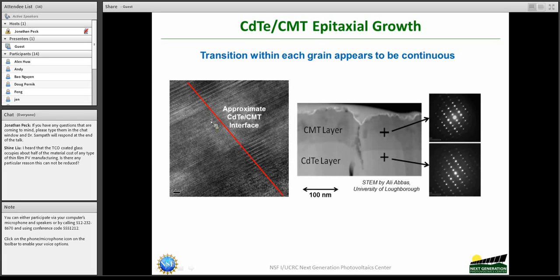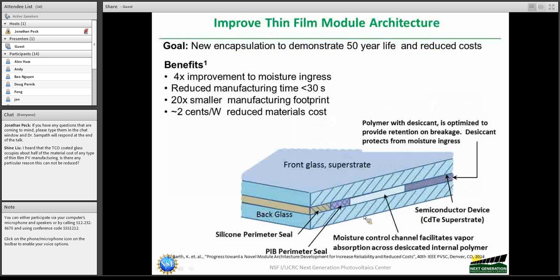And you see this at this atomic resolution TEM, and also you see this in the electron diffraction patterns, which are quite similar, and all of these results come from the University of Loughborough. Good quality of CMT done on cadmium telluride.